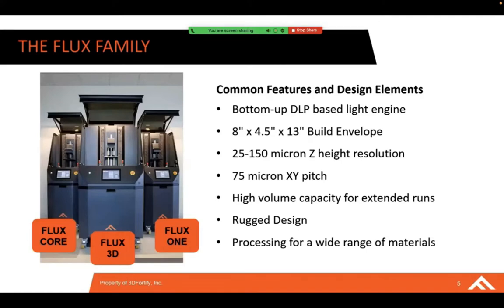DLP stands for digital light processing. Each printed layer in this process is cured by exposing an image of UV light, which is patterned by the DLP projector. And that DLP projector is the same technology found in overhead projectors in conference rooms and classrooms, except that it's tuned to expose with UV light. So our printers have a competitive build envelope of 8 inches by 4.5 inches by 13 inches, with excellent pixel resolution and a wide range of achievable layer thicknesses.